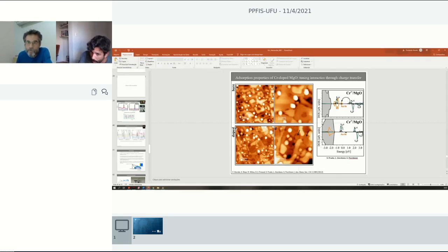Okay. So if you change the oxide or the dopant, you are going to see, of course, that the conduction band or the valence band are more or less aligned to these metal states. And then this promotes, of course, different occupation of the orbitals. But it's populating states that maybe were not populated, it's not really changing completely the states of the particle itself, like in a quantum dot.